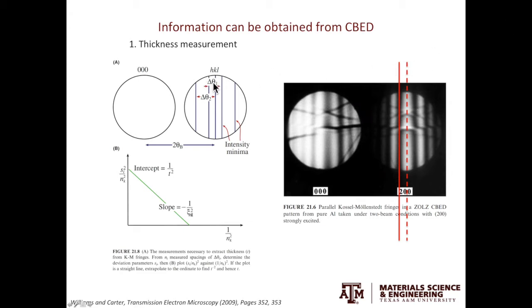Let's call that delta theta 1. Repeating the same process, now let's locate the second dark fringe. And the distance between the center line and the second dark fringe, let's call that delta theta 2. You can further repeat the process to get delta theta 3, delta theta 4, etc.